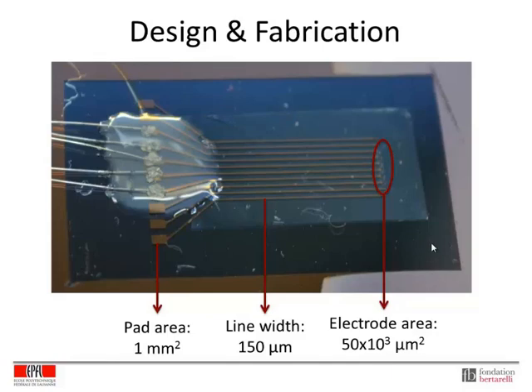Now I'm going to show you how we make our soft electrodes using primarily PDMS. This is a general top view image of our electrodes. This all the way on the left is the pad area, which are about 1 millimeter squared. And on the right we have our electrode area. Everything on the top is encapsulated except for the openings of the electrodes, and the electrode area is about 50,000 square microns.